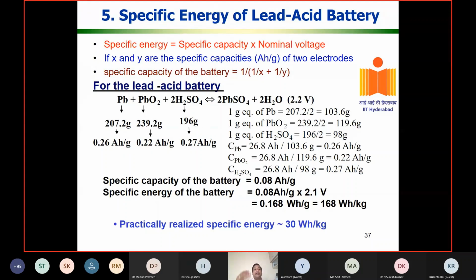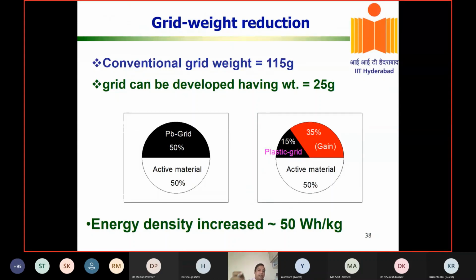So if you calculate the energy density, the practical realized energy density in the flooded cell is around 25 to 30, and in the VRLA cell is around 30 to 40 watt-hour per kilogram. It's very low because it's heavy. In the past, we tried to make even lightweight VRLA cells. I'll come to that. So I have put it here. I wanted to tell you here itself in case I miss it. Simply see, the lead grid is around 50% of the weight, and this is only for the current collector. It doesn't give capacity. It adds extra weight to the battery. You can think, can I develop some lead grid which is stable in sulfuric acid and has less corrosion, so that I can reduce the weight? You can reduce it significantly.